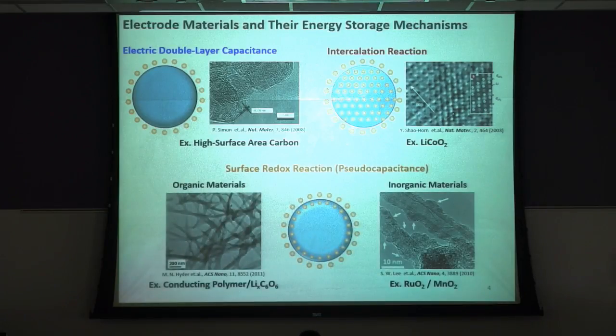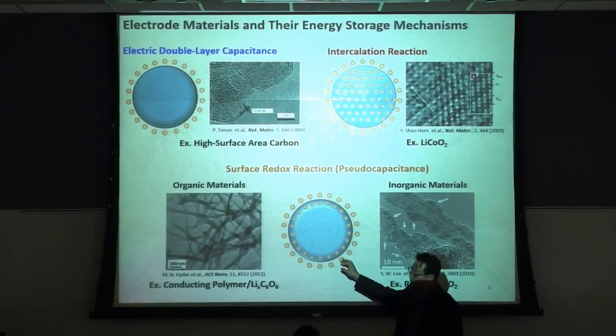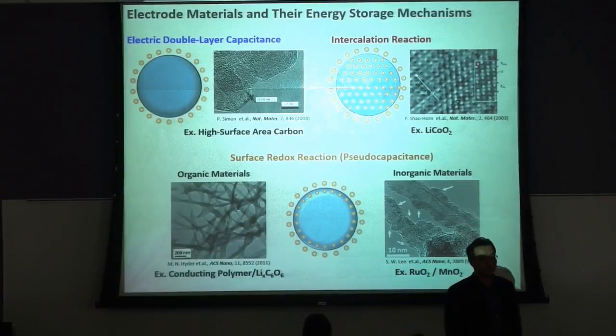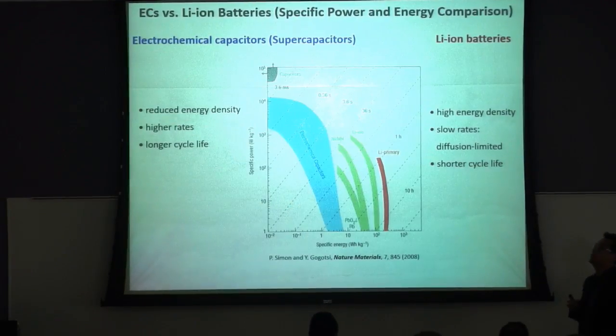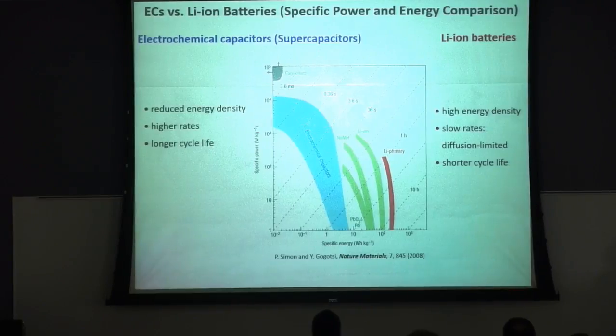In between, there is another type of energy storage mechanism called surface redox reaction or pseudocapacitance. Some organic materials, such as conducting polymers, can store charge based on the adsorption of anions on the backbone. So we call that the surface redox reaction. Also some inorganic materials, such as ruthenium oxide and manganese oxide, can store charge on the surface and the near surface region. Here, electrolyte ions can penetrate a little bit into these materials. The penetration depth of these pseudocapacitance materials is around tens of nanometers. So based on this charge storage mechanism difference, we can expect performance differences in the energy storage devices.